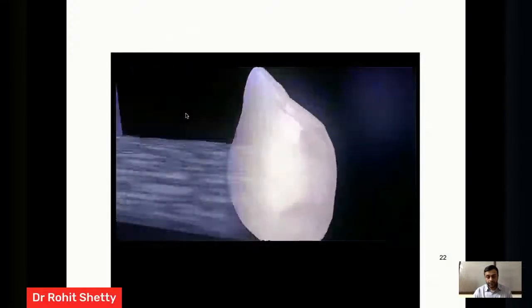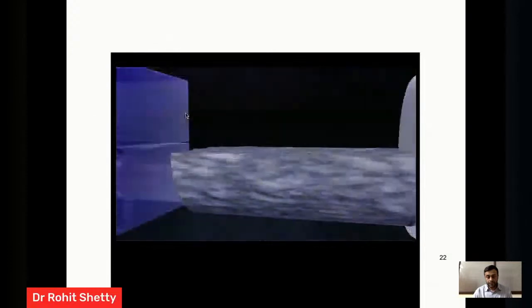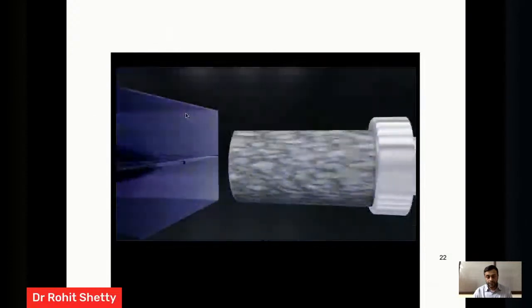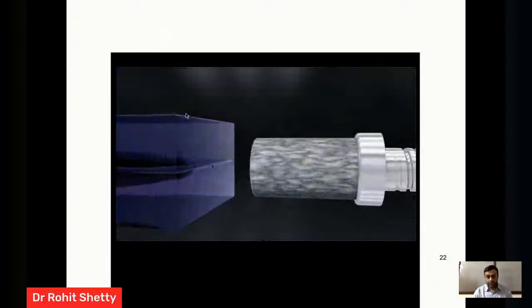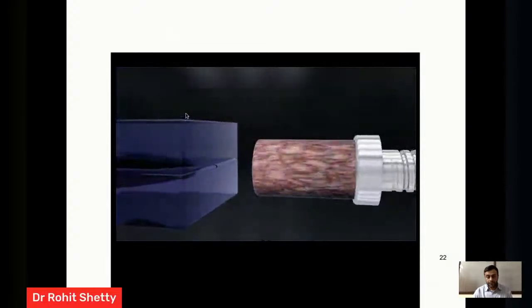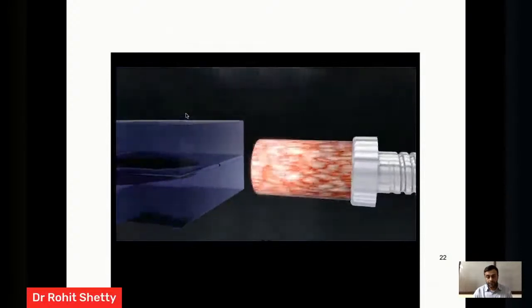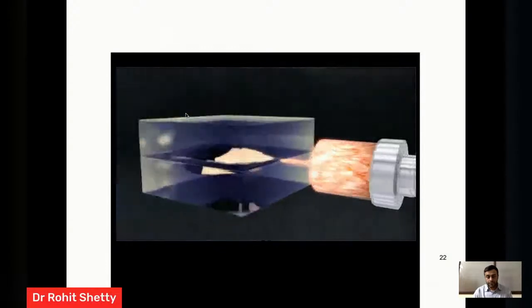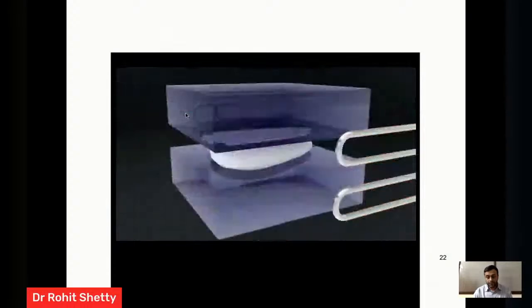The basis consists of a highly filled homogeneous nanohybrid composite material. In a first step, this material is heated and injected into special molds. At over 300 degrees Celsius, the mass is now polymerized thermally as well as through light and tempered for half an hour. This results in a solid and yet flexible blank.